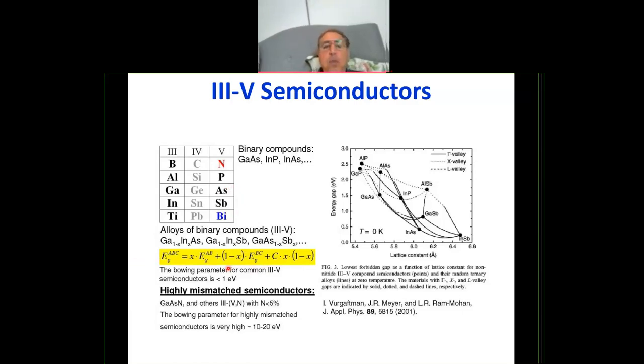Okay, so there were so many theories about finding the energy gap. Because it was very difficult to grow this material system, for example, gallium arsenide nitrogen or gallium arsenide with bismuth, because you're trying to replace an atom with something either smaller or bigger than it. Bismuth is bigger than arsenic, but nitrogen is smaller than arsenic. So you change the lattice, you create some defects in there. So this is the idea.